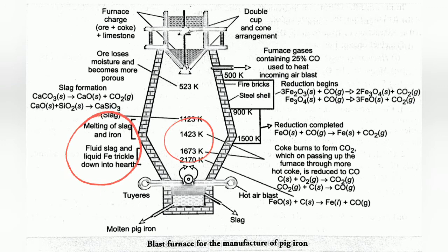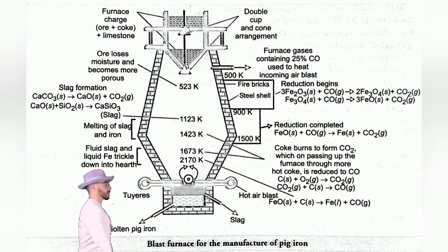The lower part of the furnace is the zone of fusion, where the temperature is between 1423 to 1673 Kelvin. In this region, spongy iron melts and dissolves some carbon, sulfur, phosphorus, silicon, manganese, etc. Sulfur, phosphorus, and silicon are produced from sulfates, phosphates, and silicates respectively, which may be present in the ore, by reduction with carbon. Calcium silicate slag also melts in this region. Both the molten slag and the molten iron trickle down into the hearth where they form two separate layers. The molten calcium silicate slag being lighter forms the upper layer, while the molten iron being heavier forms the lower layer. These two liquids are periodically tapped off from the two holes provided in the hearth.